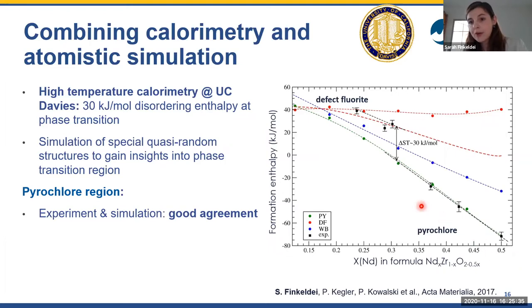Over here, you can see the black data points, and sorry, this is a little messy, maybe harder to see. These are the formation enthalpies for pyrochlore samples. And once we go backwards on these axes, we replace more of the neodymium by zirconium, and that ends us up in a defect fluorite structure. When we performed computational analysis with special quasi-random structures, we could easily describe our experimental data in the pyrochlore region with a pyrochlore model. But when we tried to describe these three, the defect fluorite structures, that was not easily doable with a defect fluorite structure.